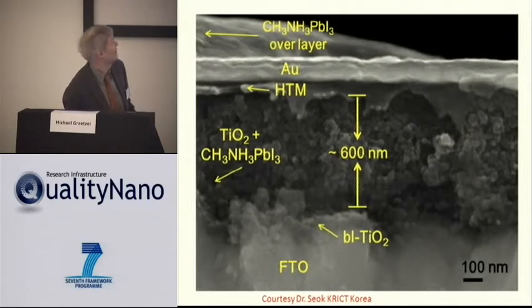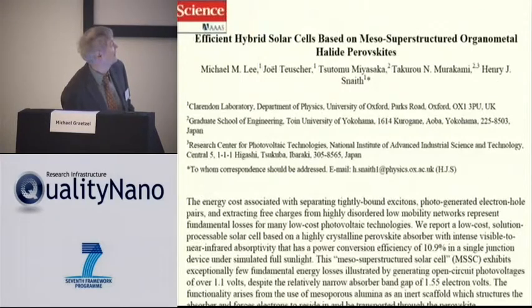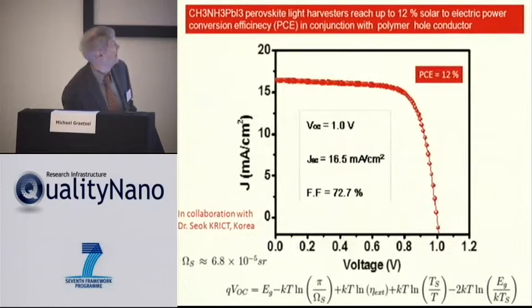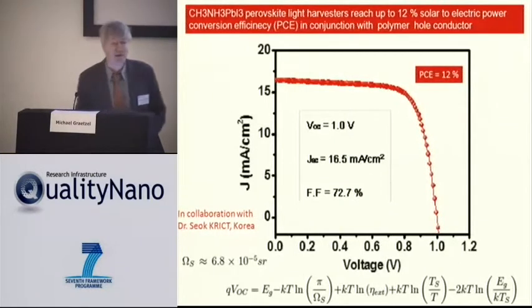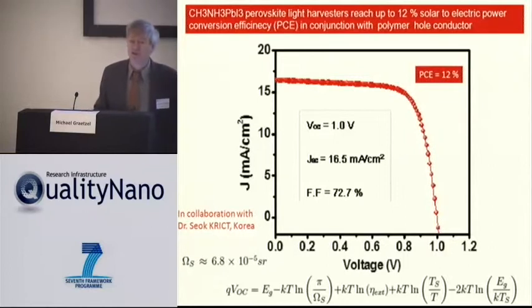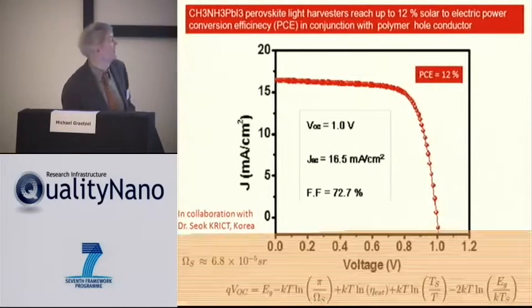But the truth of the matter is, even though we have much thinner films than with the molecular sensitizer, we get high efficiencies, and efficiencies reaching now over 12%. As a matter of fact, 12.3 is the highest, and also very high voltages. So this is a promising development. These pigment cells are not ready to be put in practical devices. It's clear that still is a research state, but it's very promising.